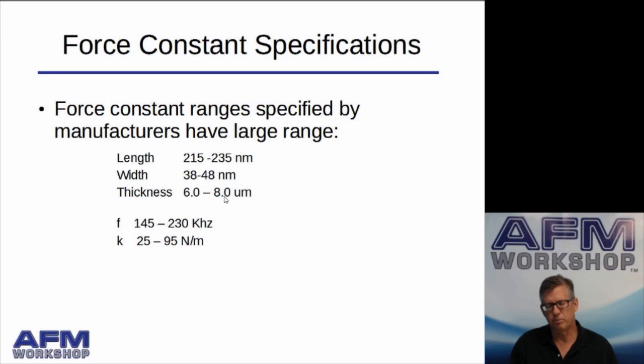And if you plug those in and you look at the extremes of what these force constants and resonant frequencies can be, it's quite large. So the force constant can vary by a factor of a little over 3, from between 25 newtons per meter and 95 newtons per meter. And that can also be nanonewtons per nanometer, the same units. But that's quite a large variation.